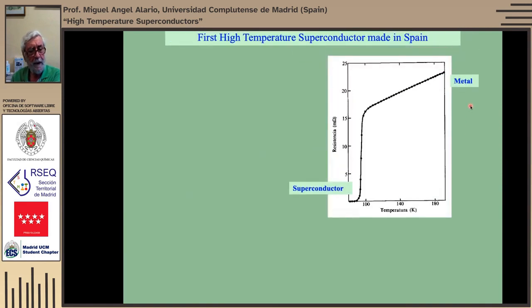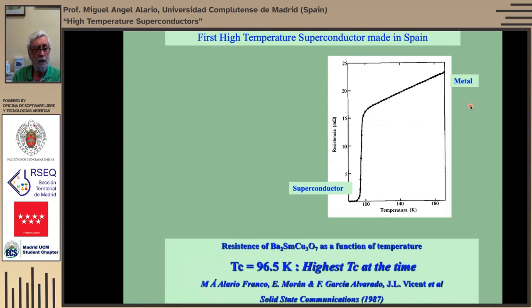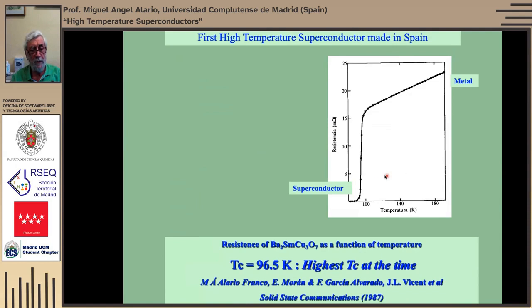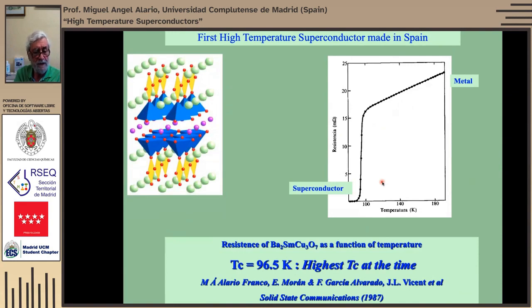I open a parenthesis just to show you the first superconductor made in Spain, because it was an interesting thing for us, for the group, and also because Emilio was very much involved. We co-directed the thesis of Flaviano García Alvarado, preparing this material. What you see is a perfect plot of resistivity for a superconductor, and the temperature at the time was the record, the highest Tc measured so far. So Emilio, as you see, is always present in our work.